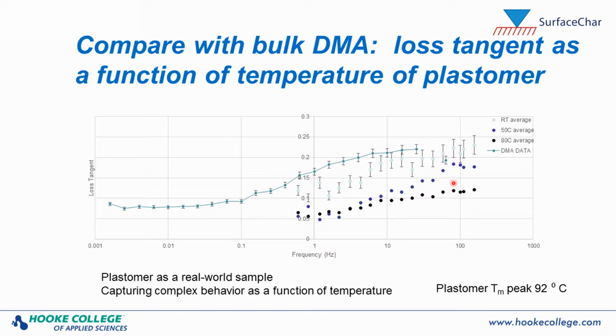And we can see a flattening of this curve as we approach the temperature for the melting point of the plastomer, which was 92 degrees. So you can see some very complicated measurements of our viscoelastic moduli, again as a function of frequency and temperature, and that can help us elucidate important structure property relationships, especially in materials which have nanoscale features or nanoscale domains that are impossible to probe in any other way.